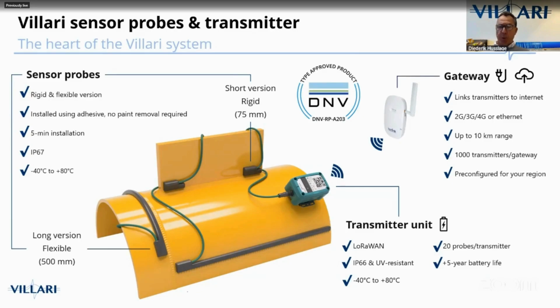The sensors have a broad range of temperature, so we run from -40 to plus 80 degrees, and the sensor system is extremely robust. To install a single sensor costs you like 5 minutes. It is putting some glue on it, holding it to the surface, and after 30 seconds to 2 minutes, the sensor is put on the object. We connect it to the transmitter box, and the sensor is immediately in operation.